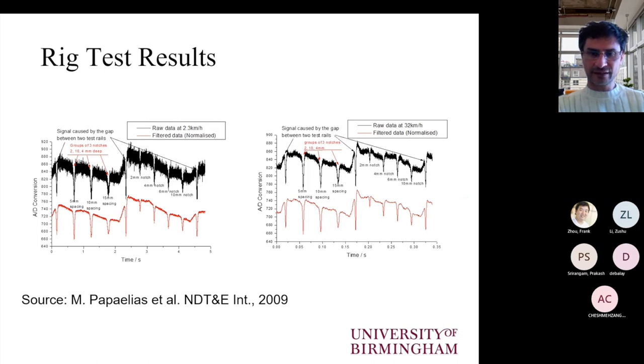You can see the signal is varying a little bit. This is because we couldn't keep the sensor at constant liftoff. So due to some variations, the background signal varied accordingly. But even then, the signals were still obtainable from the different defects.